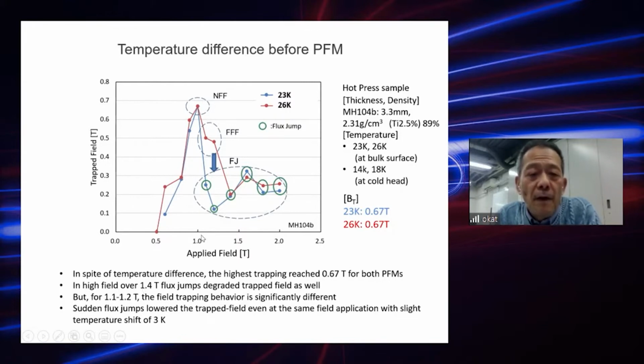The highest trapping field reached 0.67 Tesla, like this, in both PFM. But in a high field of over 1.4 Tesla in this field, the flux jumps degraded the trapped field as well. So there is no big differences between that.